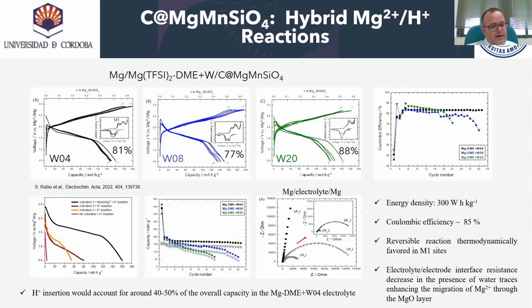We adopt an alternative approach of engaging water traces in a conventional non-aqueous solution. After a charge activation cycle, more detail about which can be checked in the reference, the electrochemical reaction of magnesium cells occurs between 2.8 and 0.5 volts versus magnesium, with 160, 150, and 162 mAh per gram of reversible capacity, when water 0.4, water 0.8, and water 2.0 is used in the electrolyte composition. The reversible reaction is thermodynamically favorable in M1 sites, as we can deduce from the derivative curve, the inset of the galvanostatic curve.